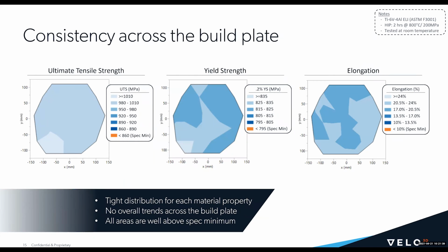So now I'd like to show you a couple different plots because we just talked about consistency. And you see right here, this is consistency across the build plate in the X and Y direction. These are Ti-6Al-4V ELI bars that were tested. We have ultimate tensile strength, yield strength, and elongation. And we're basically seeing a very tight distribution for each of these.